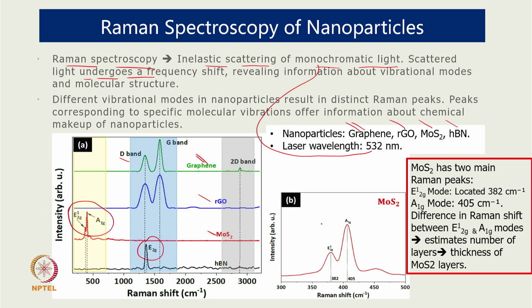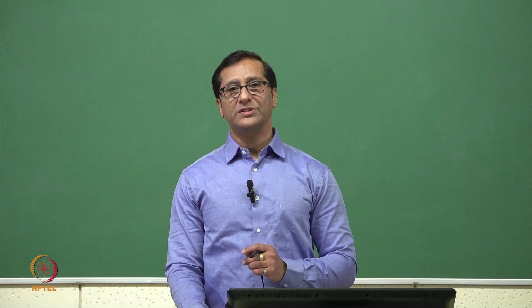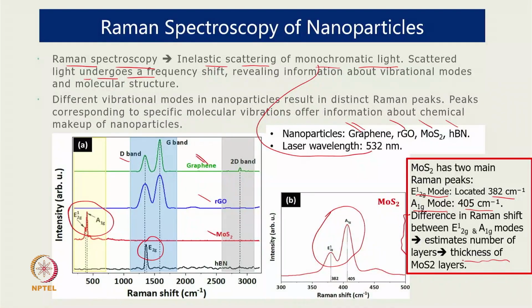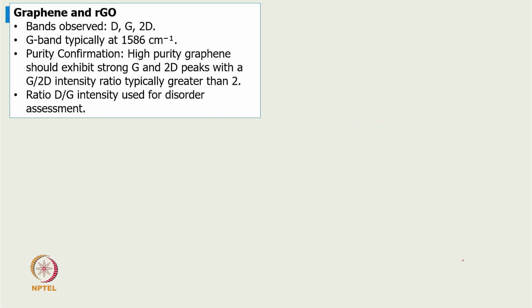So MoS2, particularly when we magnify or increase the size, we are able to see that it shows two modes. The E1 2g mode comes around 382, and then the A1g mode comes around 405. This is coming because of the difference in the number of layers, or we find some agglomeration happens, and that's why this kind of difference is coming.